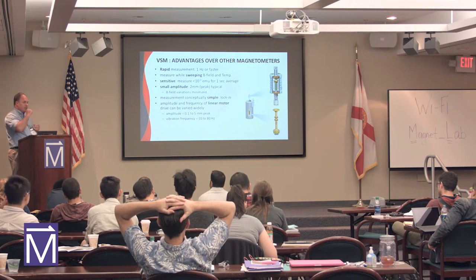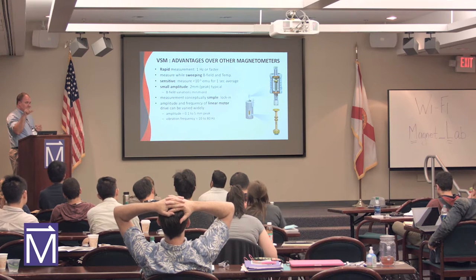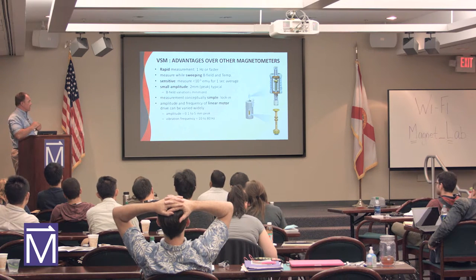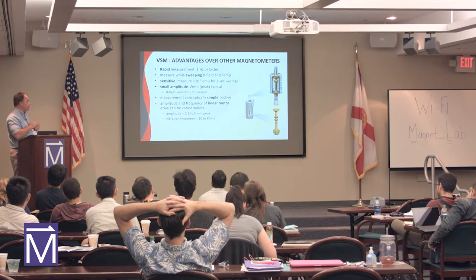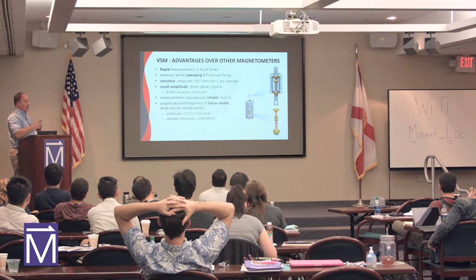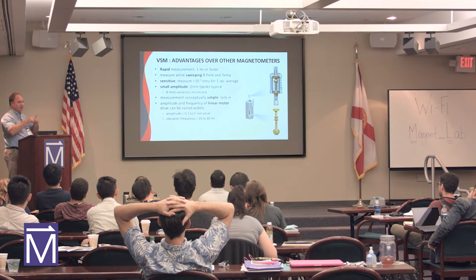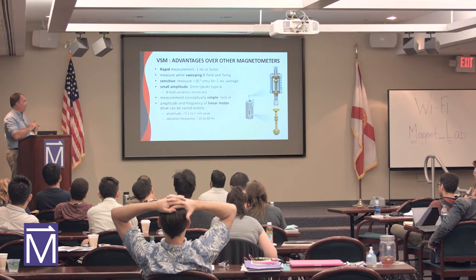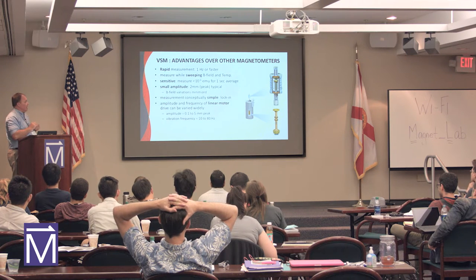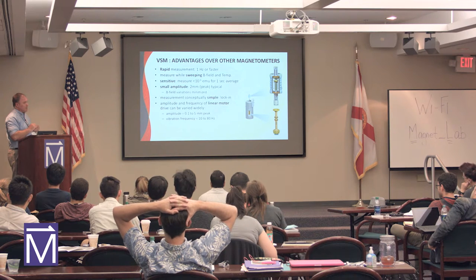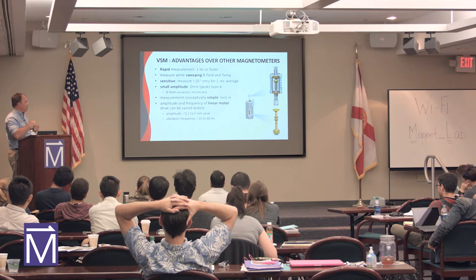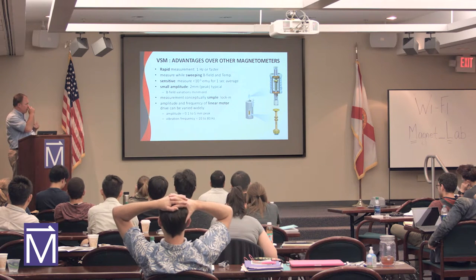It's in a homogeneous part of the field, so the field distribution variations are eliminated because it's in the homogeneous part of the field. So on the PPMS system, we have a nice plateau where the field's flat. It's about six centimeters where you've got a nice good uniformity in the field, and we're using a small portion of that.